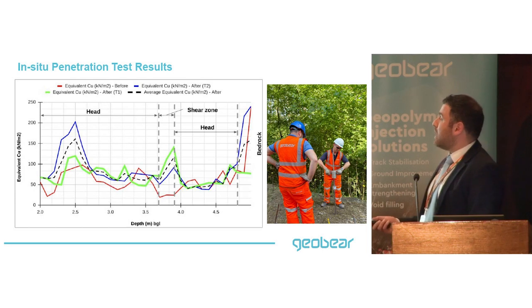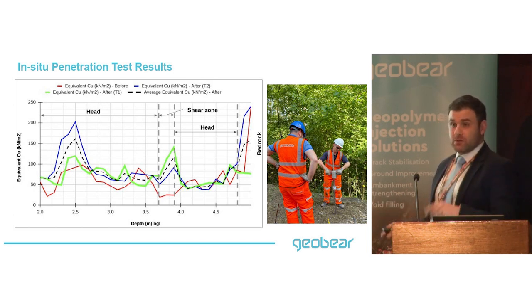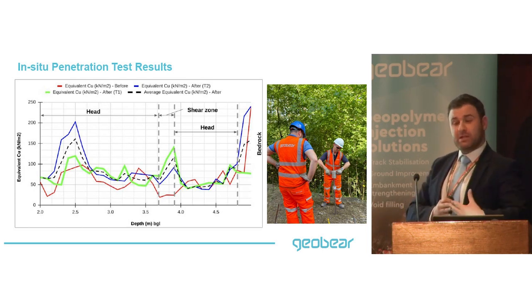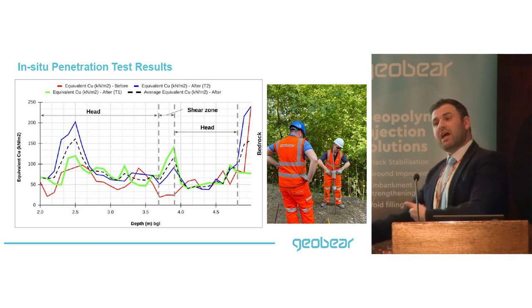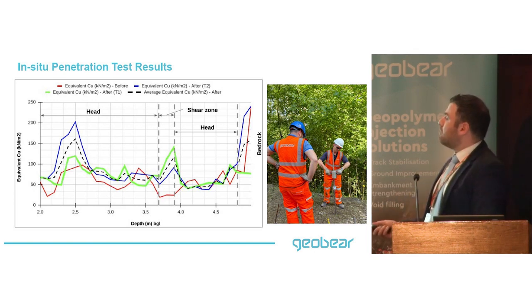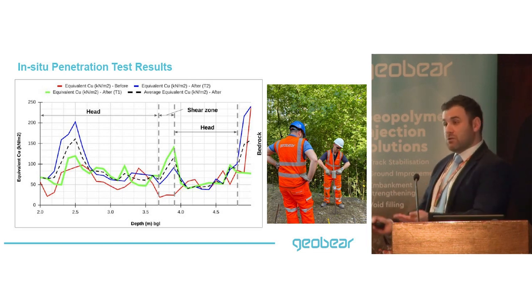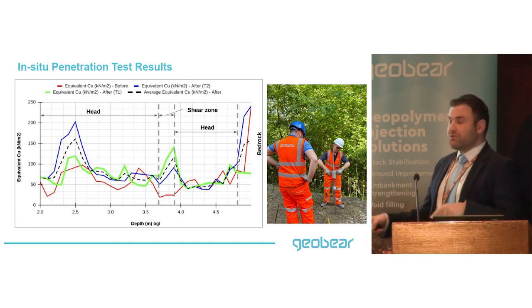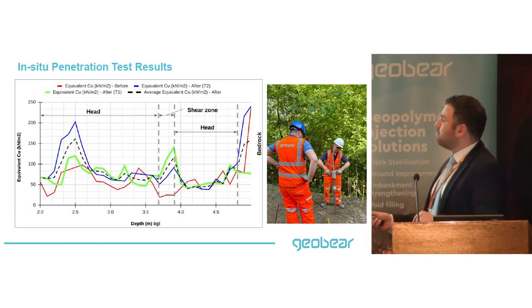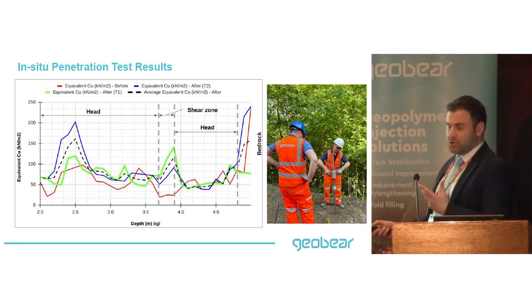We did the probing in two locations — one pre-injection and two locations after the injections. The red curve represents the shear strength across the depth from the probing before treatment. The blue and green lines represent the dynamic probing results following the injections at two different locations, and the black dashed line is the average between them.